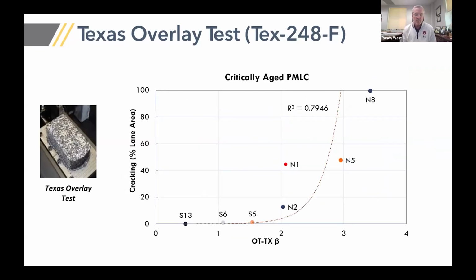If we look at the XY chart, you see that R squared here is about 0.79. That's a very strong correlation for a field test under controlled conditions. So we're really happy with this test as a good indicator of top-down cracking.